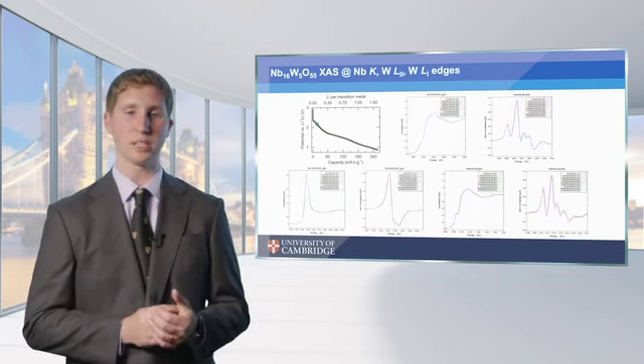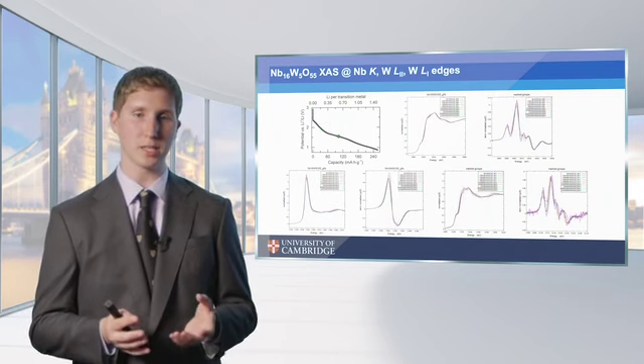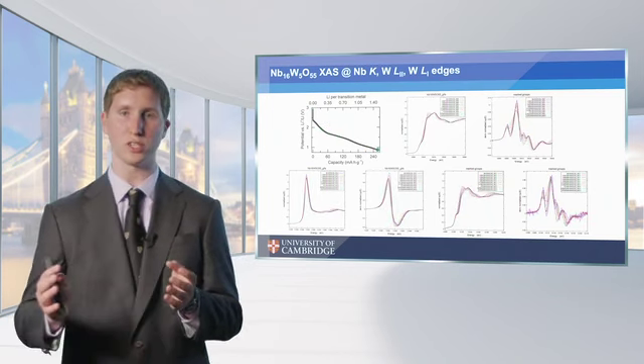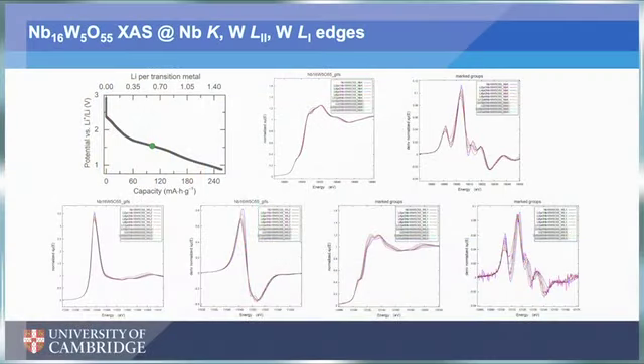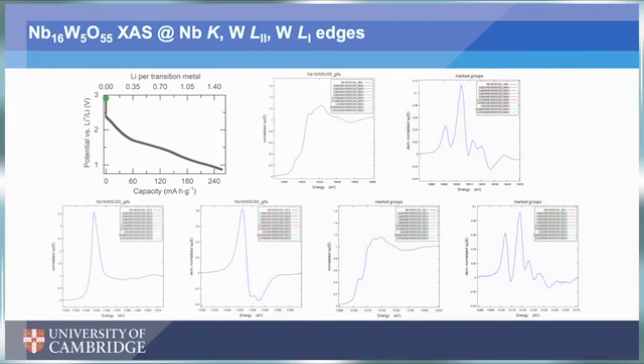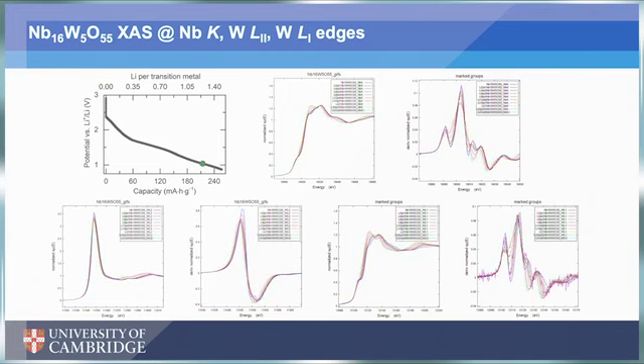And so this gives rise here to a pre-edge feature because the second-order Jahn-Teller distortion causes an off-centering of the transition metal. And this off-centering then has implications for the long-range structure of these atoms as well. But what we observe is that as we reduce our transition metals, we should see a removal of this distortion and therefore actually an increase in the local symmetry of our octahedra, so becoming less distorted. And also that should be correlated then with a decrease in our pre-edge feature.